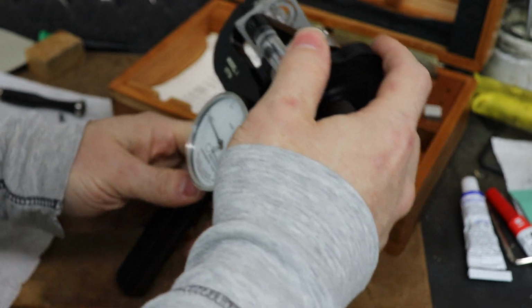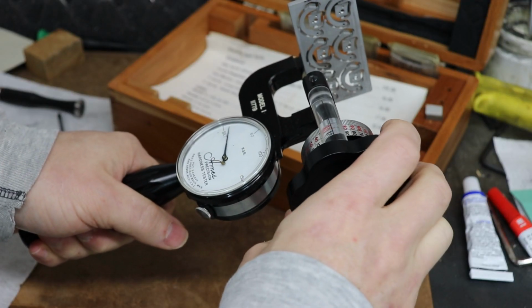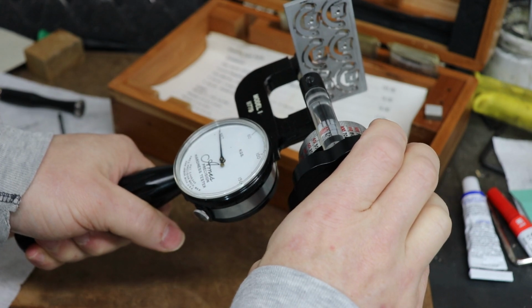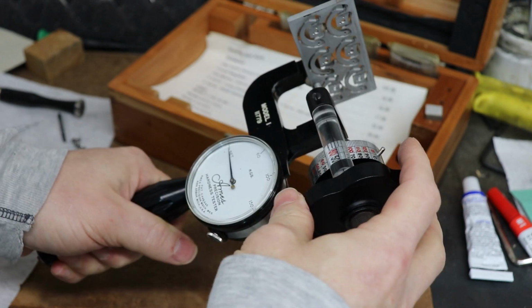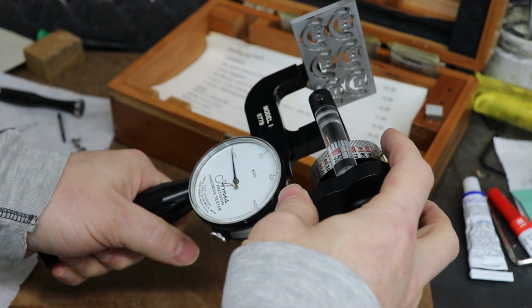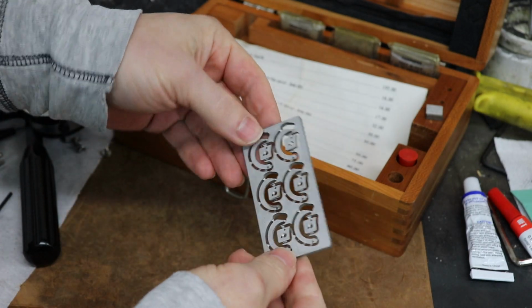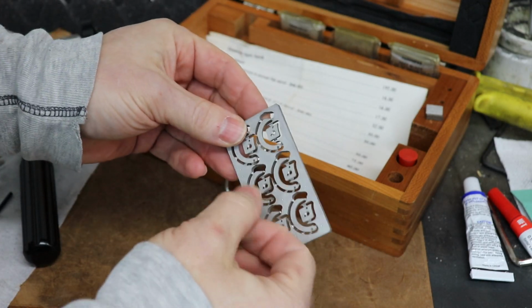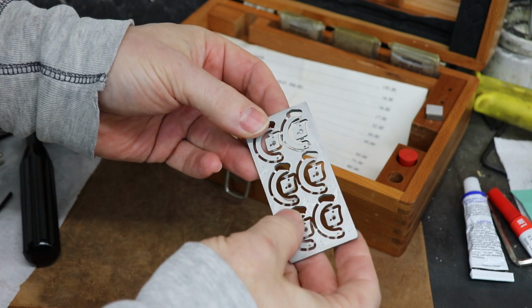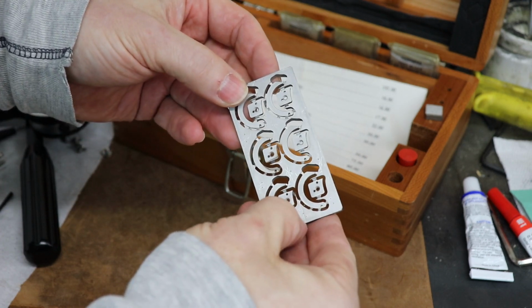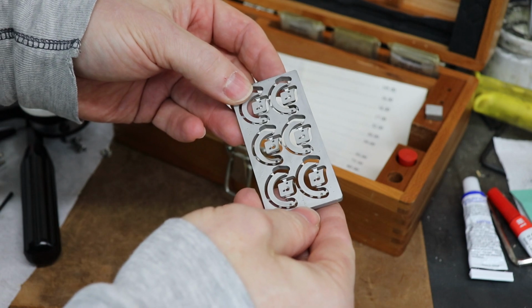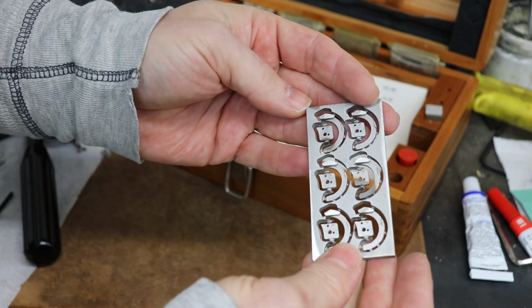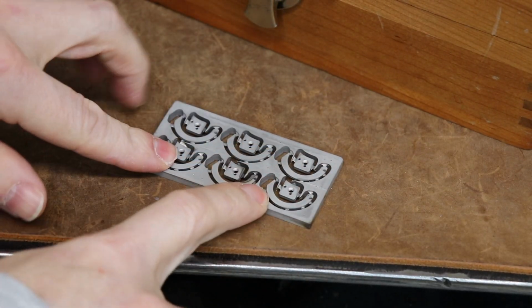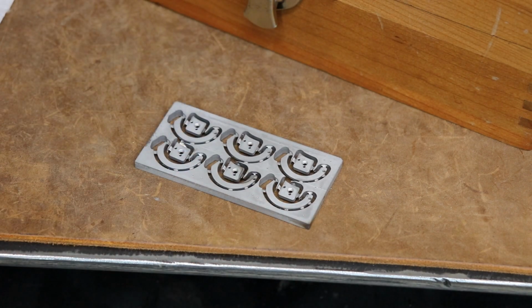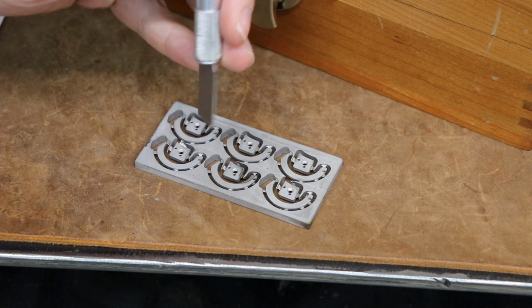56, 57 Rockwell. So I tested a few different spots, getting 56 to 57 Rockwell, which is good for these parts. You don't want them to be too hard. Also, they need to be hard enough so they don't wear down real easy. Now that I know I've got the hardness within the range that I specified, I need to pull these out.